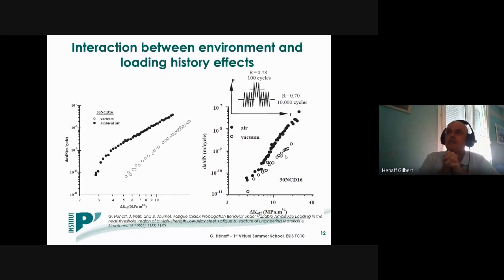On this slide, you have an illustration of possible interactions between environmental effects and some loading history effects, which are more representative of the actual loading that can be seen during service. So in that case, it's in the case of a low alloy high strength steel used in some helicopter rotor components. So on the left-hand side, we compare the fatigue crack growth rates obtained in air and in vacuum.